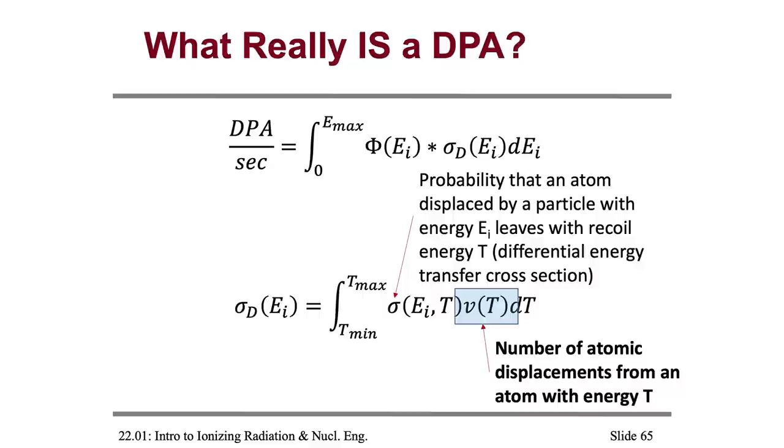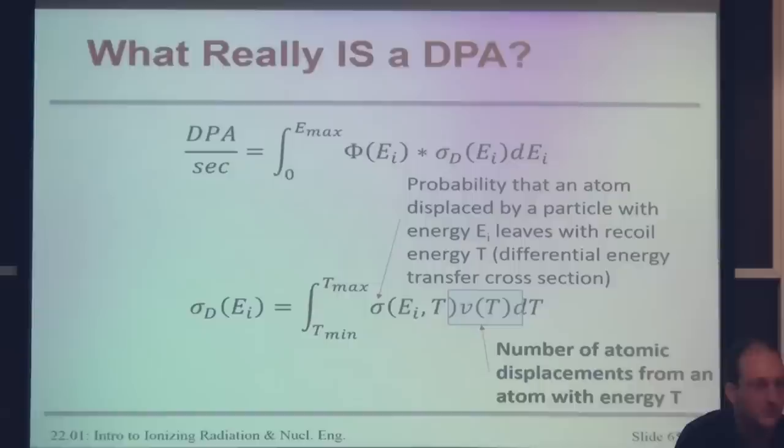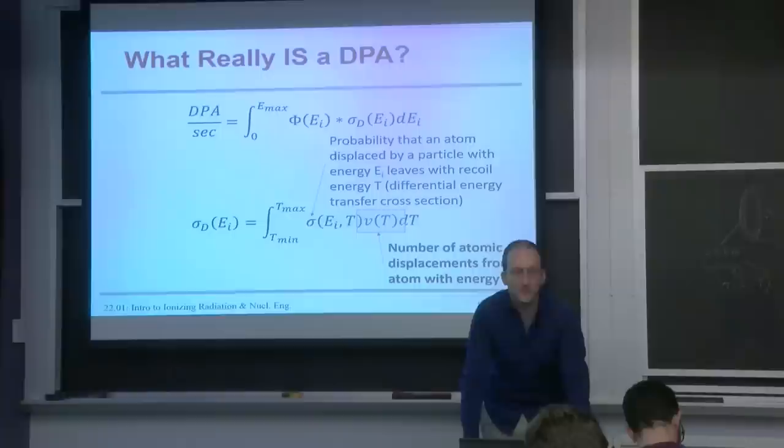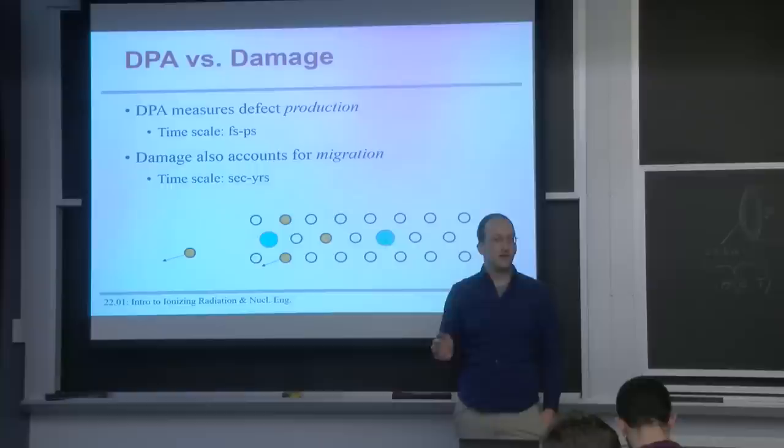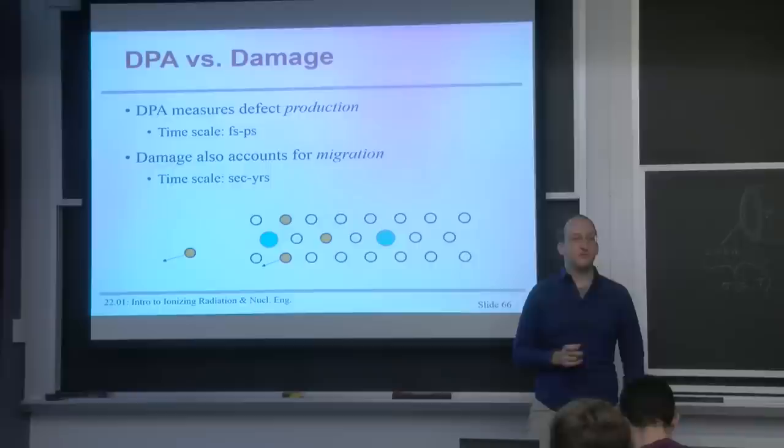And we wanted to know, well, for all possible approach paths, the area of this hollow circle or the probability that this particular approach path is taken is just the area here, 2 pi b db, with some constants in front of it, which actually is that cross section. What's the probability that our particle goes in with energy E and imparts kinetic energy T? It's directly related to that impact parameter b. And this is the same thing that you're seeing right here. You then multiply by this little function nu of T, which represents the amount of damage or the number of displacements done for each one of these reactions. And there are simple models, mostly linear models for if a particle comes in with energy E, leaves with energy T, how many displacements happen.